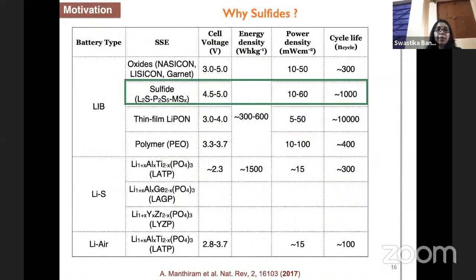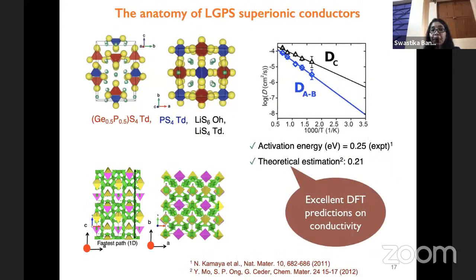So if we think of solid electrolytes like sulfides or several oxides, oxynitrides, in terms of their performance, we find sulfides are quite promising in terms of the cell voltage, power density, or cycle life. However, there are promising oxide electrolytes or polymer electrolytes, which still need some more study to be understood well in terms of their practical applicability. So why sulfides? Their softness, their applicability to make the device setup. And it is the famous LGPS framework, as I have told you, whose conductivity is competitive with the liquid electrolyte.